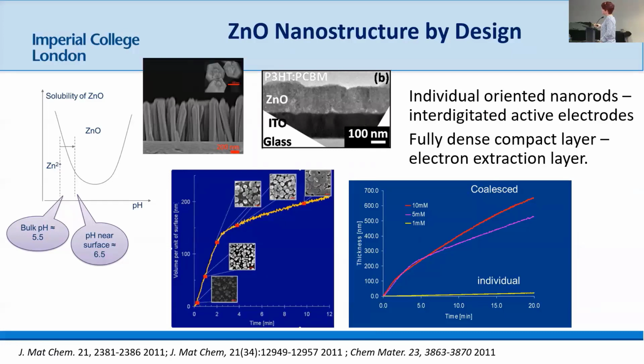So eventually we ended up with quite a large design map, actually, based on understanding growth and time and conditions, where we're able to say, okay, for this project here, which was a project where we were looking at creating active electrodes for using a solar cell, I can make perfectly interdigitated one-dimensional systems, and they lock into the polymer system that we were looking at in this paper. And they're all orientated in this direction, which is fast transport direction.